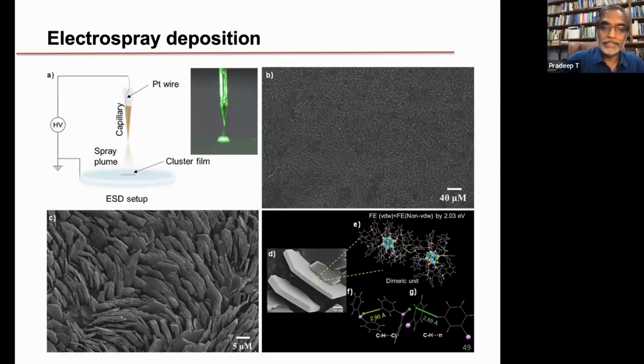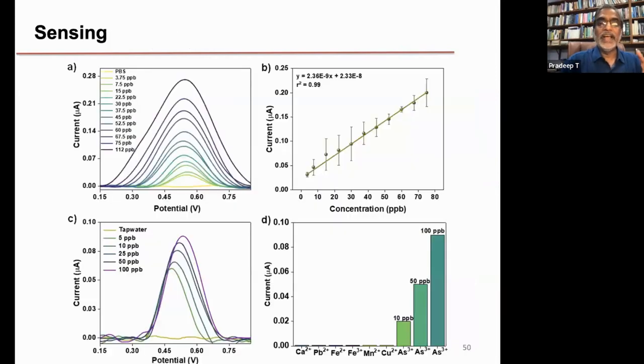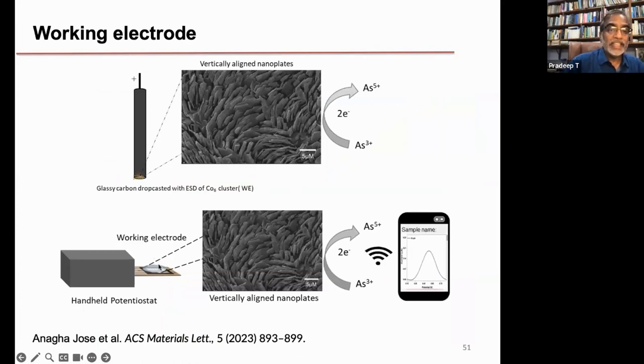So what is so exciting? These are specific surfaces, and these surfaces can detect arsenate and arsenite, in this case arsenite. And you see the specific kind of oxidation that is happening. Even down to about 3.75 parts per billion, you get a big peak. Which means that you can measure even down to 1 part per billion, and that without pre-concentration, directly from water. And what it means is that you can measure these concentrations and put it on a tiny device.